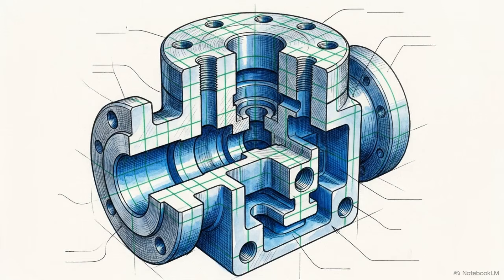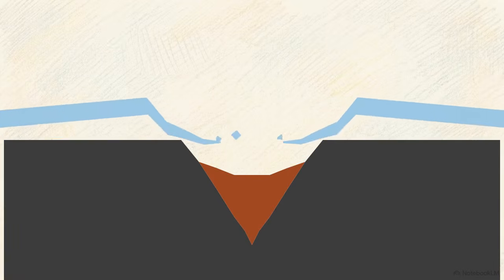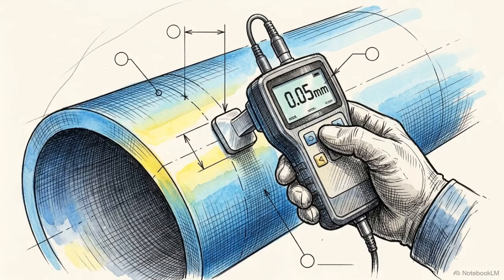Complex parts require absolute uniformity in coating thickness. Even a microscopic gap in coating coverage leaves the component vulnerable. A localized thin spot inside a crevice becomes the initiation point. Corrosive elements easily bypass the shield, hollowing out the structure from the inside and causing perfectly sound coating above it to detach. Without non-destructive thickness measurement tools to strictly verify adequate uniform coverage, a surface-engineered part is an invisible failure waiting to happen.